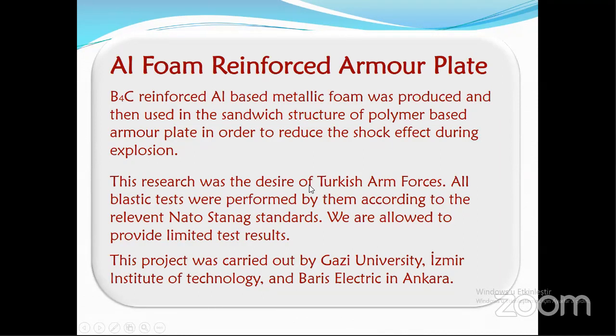Aluminum foam reinforced armor plates, I would like to mention. Boron carbide reinforced aluminum-based metallic foam was produced and then used in the sandwich structure of a polymer-based armor plate in order to reduce the shock effect during explosion. This research was the desire of the Turkish Armed Forces. All ballistic tests were performed by them according to the relevant NATO STANAG standards.